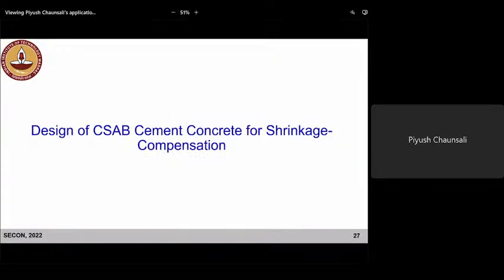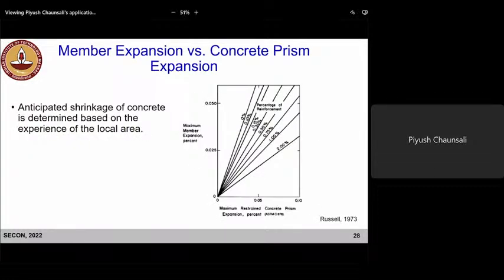So this is the final section where we'll look at how do we design CSAB cement concrete, right? So we have a cement. Now let's say if you want to prevent shrinkage cracking, how do we use this cement to design that? So there are some design charts. Based on the location, we know that this much of shrinkage compensation is needed, right? Because shrinkage is driven by environmental conditions, like temperature, relative humidity, etc.